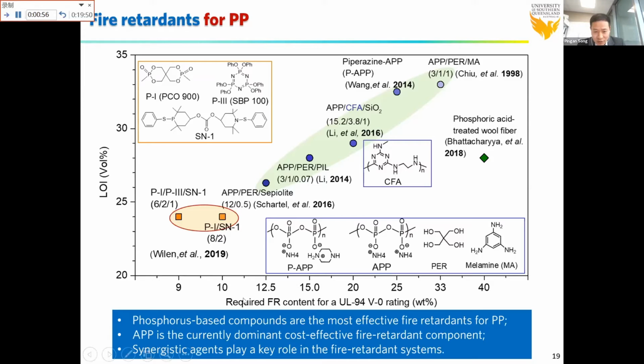So this figure just shows the loading level required to make PP reach the desired UL94 V0 rating. Initially, 33% was required to make PP get a V0. So in the last decades, research has focused on developing synergistic agents for APP to reduce that. In 2016, they reported the use of sepiolite as a synergistic agent for APP. At 12.5%, you can get a V0 rating, the desired rating, although its LOI is not high enough.